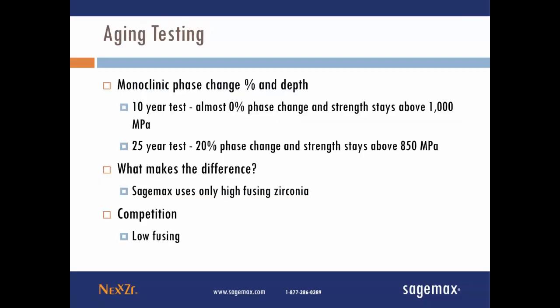So aging testing is another type of test that we can do at our in-house facility. We actually do two different ones: a 10-year test and a 25-year test. What the aging testing is really looking for is called a monoclinic phase change. So we're looking at the phase change and the depth of that change. What we see when we test our zirconia is that after doing the 10-year test, it's almost 0% phase change, and we're able to keep a strength above 1,000 megapascals. For the 25-year test, we do see a 20% phase change, but the strength still stays very high at 850 megapascals. So what happens to make this difference